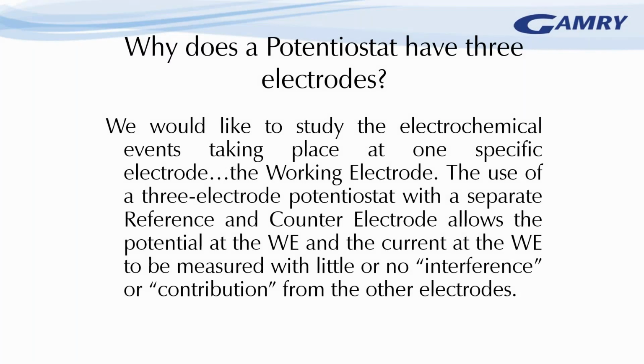So why does the potentiostat have 3 electrodes? The reason for that is we'd like to study the electrochemical reactions or events that take place at one specific electrode, the working or sample electrode. So the use of the 3-electrode potentiostat allows us to separate the reference and counter electrode. The current flows between the working electrode and the counter electrode, and the potential is measured between the working electrode and the reference electrode, with no current, or very little current, flowing in the working electrode reference electrode circuit, and so there's little or no interference from the other electrodes.